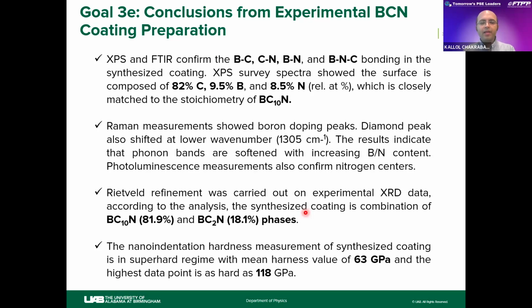Now the conclusion from this BC10N project: XPS and FTIR confirm we have BC, CN, BN, and BNC bonding in the synthesized coating. XPS survey spectra also showed that the surface is composed of 82% carbon, 9.5% boron, and 8.5% nitrogen, which closely matches the stoichiometry of BC10N.